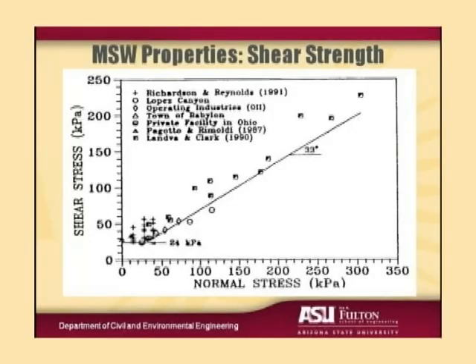One of the important things that came out of that collection of information was this plot on the shear strength of municipal solid waste. And when I first started working on OII, when I first started working in solid waste, which wasn't long before that time, there were papers in the literature that suggested that the shear strength of solid waste could be represented with a friction angle of 20 degrees. Well, you just have to look at a 1.5 to 1, 60-meter high slope, and hopefully you'll recognize that 20 degrees is a little bit conservative for the shear strength of municipal solid waste. If it was 20 degrees, it would just be in a big pile on the freeway.